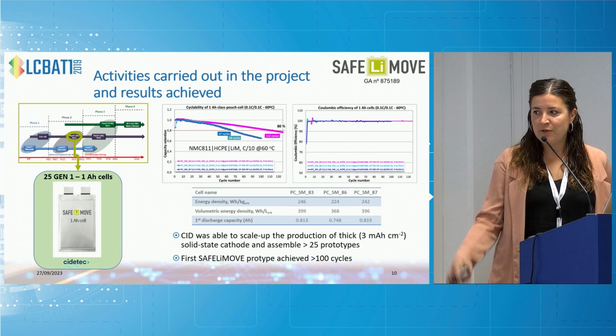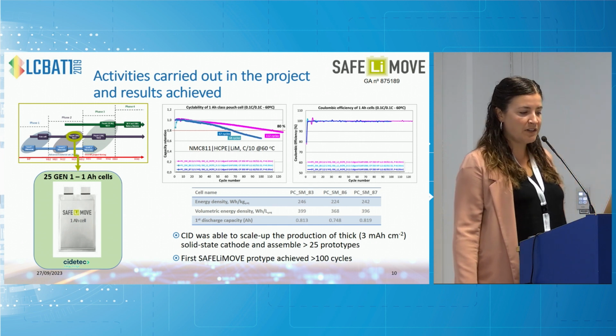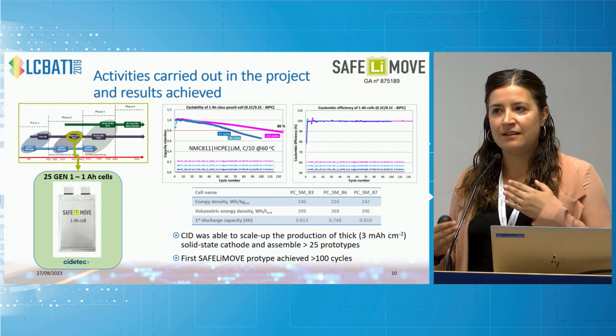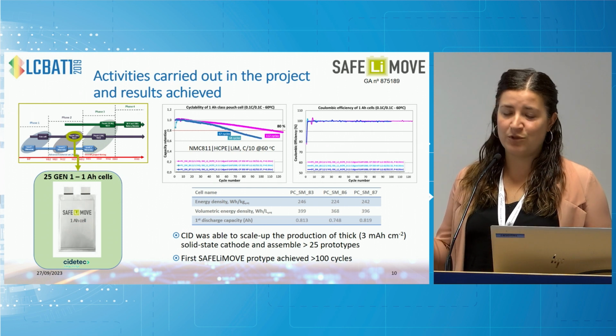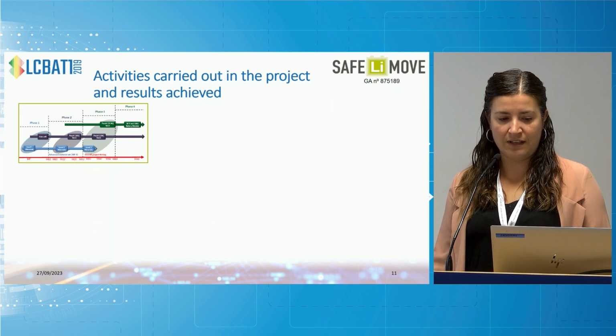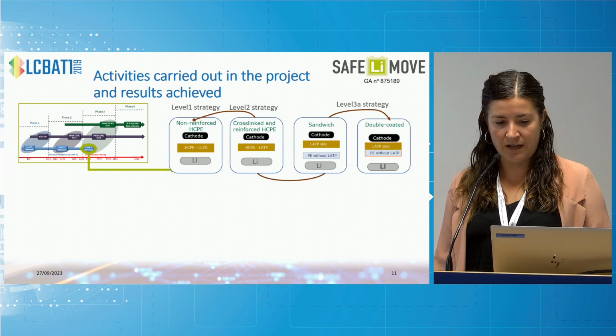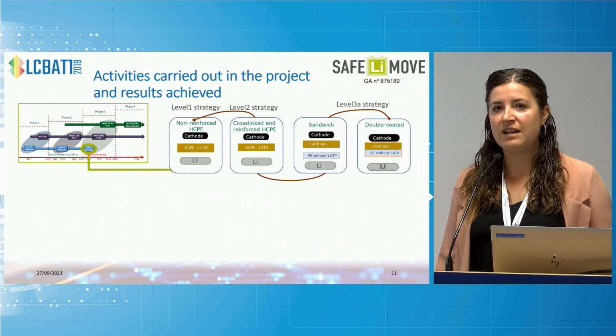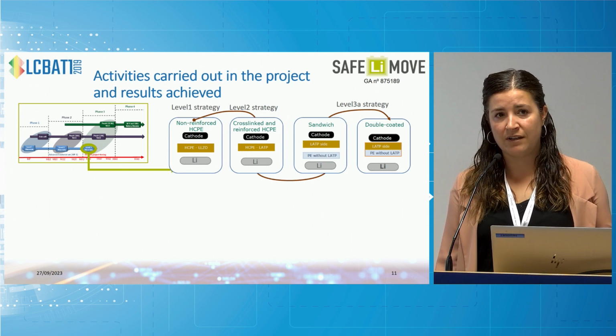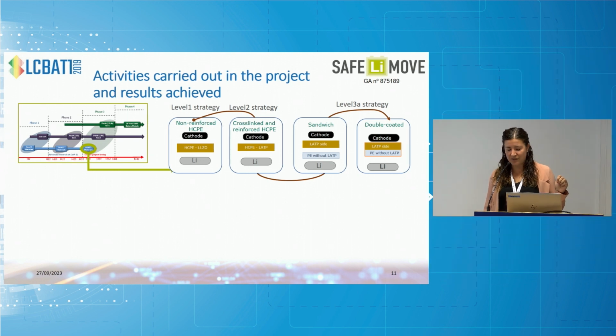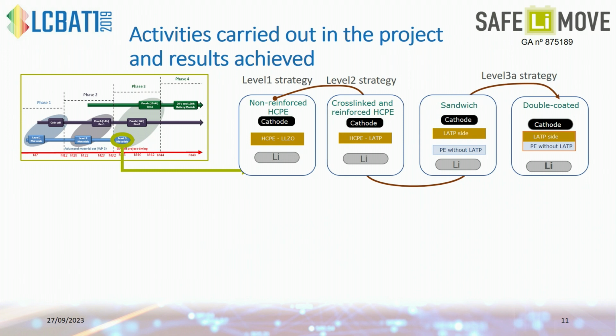As I was saying before, we were able to reach 100 cycles with these first prototypes, and then, again, the analysis of the interfaces post-mortem allows us to work on the next generation of materials. Mainly, we continue improving the coating of the cathode material. We continue working on the composition of the electrode, mainly with different additives, trying to increase not the loading, so we kept the loading constant, but the active material content. Of course, this has an impact on the energy density.